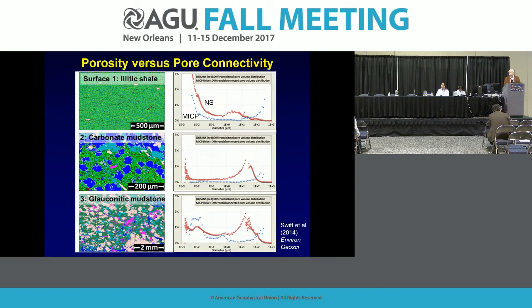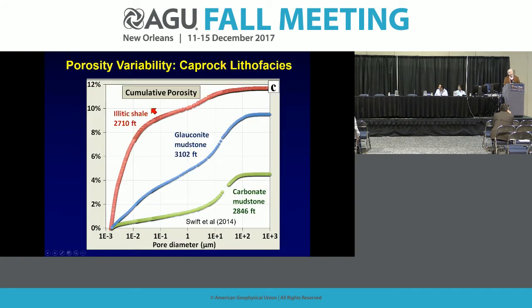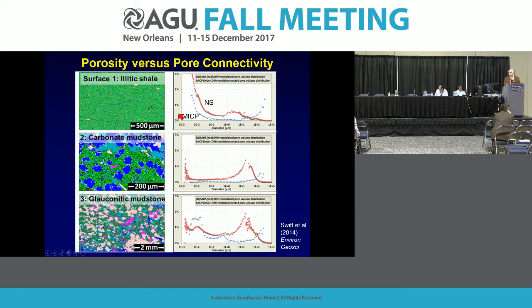So we can look at what those features look like if we look at these mineral maps that we've taken with our SEM. Again, illitic shale, carbonate mud, and glauconite. And we see very different fabrics that then result in these very different kinds of pore distributions. I should say, if I go back one, this is total porosity now, not just connected porosity. This is total porosity. In this particular plot, I'm not sure you can see these, but we've got two kinds of pore distributions plotted on the right panel.